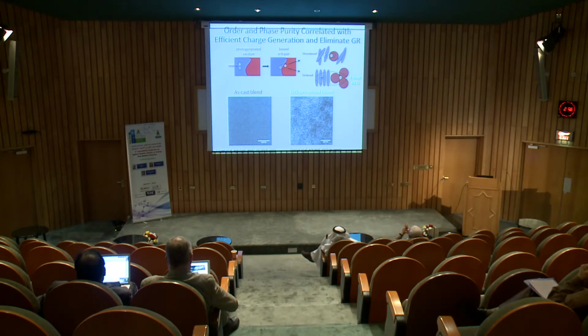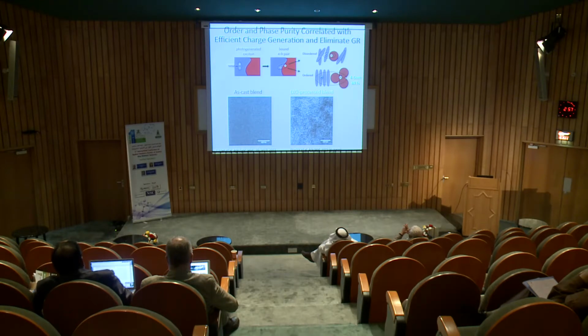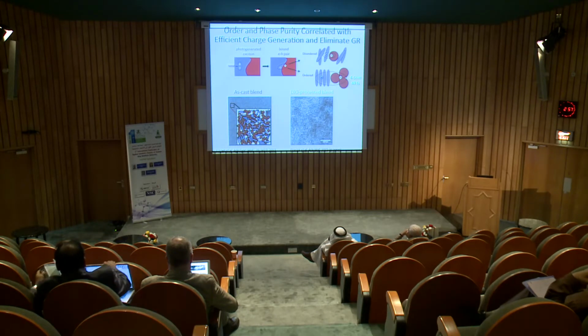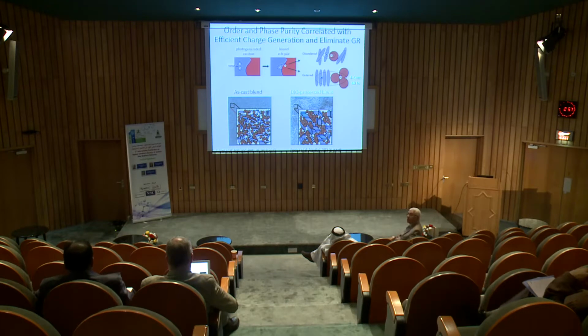But if you look at the DIO processed film, it becomes more ordered. So what does it mean that it becomes more ordered? It means that when you create the electron-hole pair, it can now delocalize over a larger unit, and because of the delocalization, it's much easier to form free carriers, and you do not need the additional driving force of the electric field to form free carriers. So you can see here, it really depends on the local order of the donor and acceptor domains that can impact the type of losses in the device. This cartoon drawing shows that in the as-cast film, you have amorphous and strongly mixed domains, and that's why they really affect the type of losses present. On the right-hand side, where you have percolation pathways and quite ordered domains, you do not need an additional electric field to separate the charge carriers. So this really helps explain how our device works.